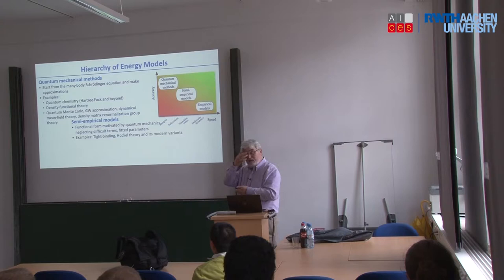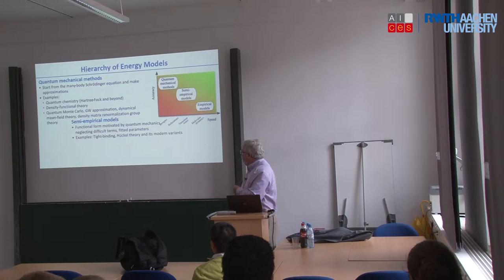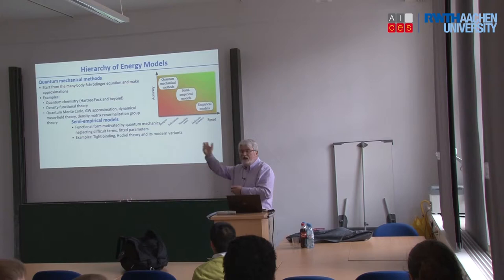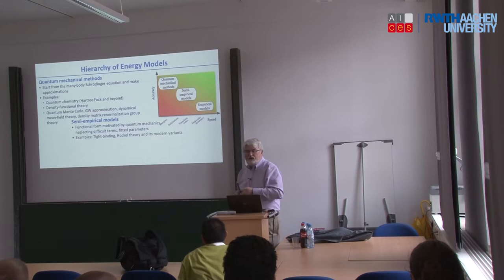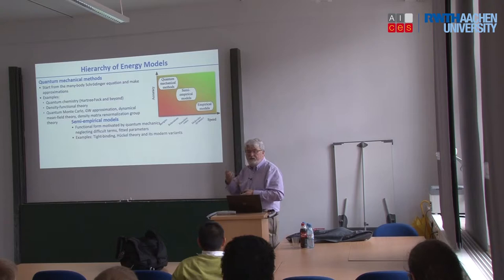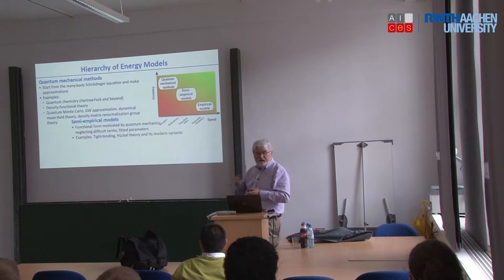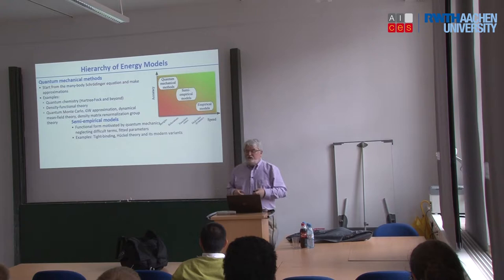In DFT, we're talking about 100 to 500 atoms, maybe 1,000. And in some of these quantum chemical methods, if you're trying to get very high accuracy, which some of them can do, then they scale as order of the number of electrons to the 7th power or 9th power. They're very good, but they get very, very, very expensive. So people can still usefully look at the nitrogen molecule.